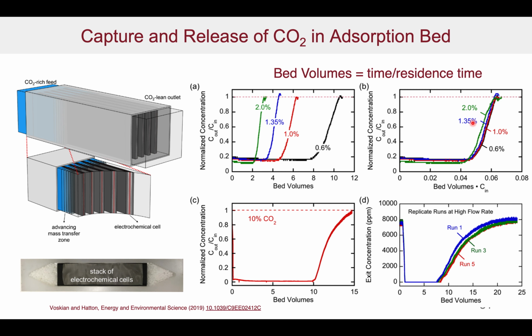Of course, that's not the way we're going to operate in a real-world situation. What we'd want is an adsorption bed, in which we have the electrodes in the bed, as shown here. This is a stack of electrochemical cells. We introduce the CO2 at a certain concentration on the feed side, and as it passes through, the CO2 gets absorbed, and the gas leaving here would essentially be depleted of CO2. As the bed gets filled up, this concentration front moves through the bed until eventually the total bed is saturated, and the outlet concentration begins to increase.